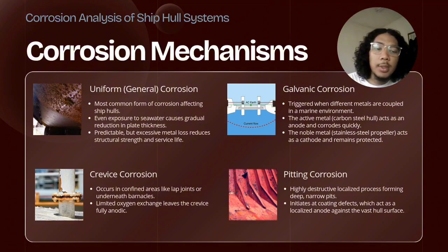Moving on to localized corrosion, which can be crevice corrosion. Crevice corrosion happens in confined spaces under barnacles or inside the lap joint. When the water gets trapped, the oxygen depletes, making the inside fully anodic. To maintain chemical neutrality, an ion hydrolysis reaction takes place.